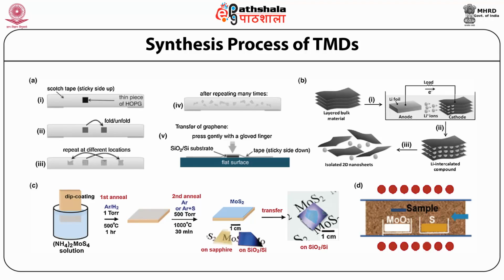These freshly cleaved thin crystals on the Scotch tape are brought into contact with the target substrate and rubbed to further cleave them. After the Scotch tape is removed, single layer and multilayer TMD nanosheets are left on the substrate.